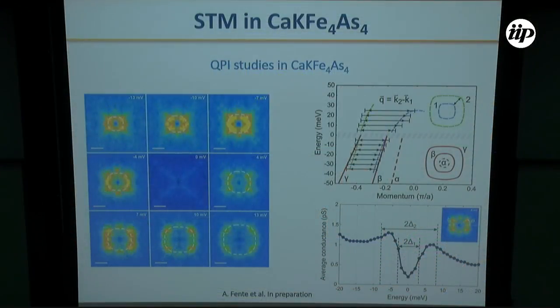So when we plot the QPI vector, we find that this scattering vector is consistent with a scattering vector between the outer and middle hole pockets obtained by ARPES data. And above the Fermi level, where ARPES data have no resolution, we find that this QPI vector increases, and then we reach the top of the middle band. As we can see, we lose the signal close to the Fermi level due to the opening of the superconducting gap.